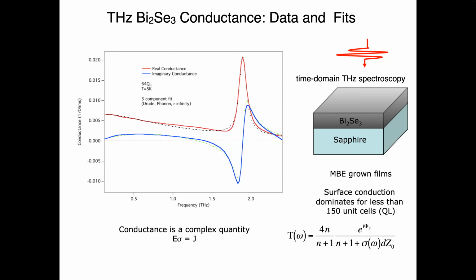A lot is known about the phonons in topological insulators because materials, before we knew them as topological insulators, materials like bismuth selenide and bismuth telluride were famous thermoelectric materials where the phonon spectrum is very important. Okay? So in the old thermoelectrics literature, that's called the alpha mode. You have an imaginary part too, and this is, as we discussed yesterday, the Kramers-Kronig transform of that.